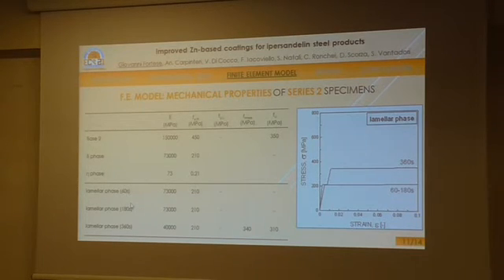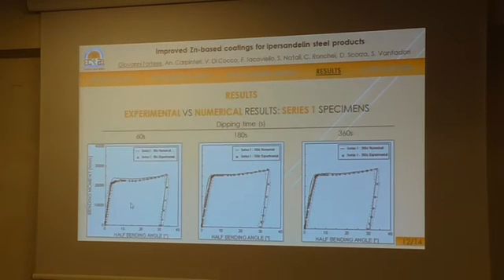The stress and strain curve related to lamellar phase is assumed to show an elastic plastic behavior for dipping time equal to 60 and 180 seconds, and a different behavior for dipping time equal to 360 seconds. In these three figures, comparisons between experimental and numerical results in terms of bending moment against half bending angle are shown for each considered dipping time of series 1 specimens.